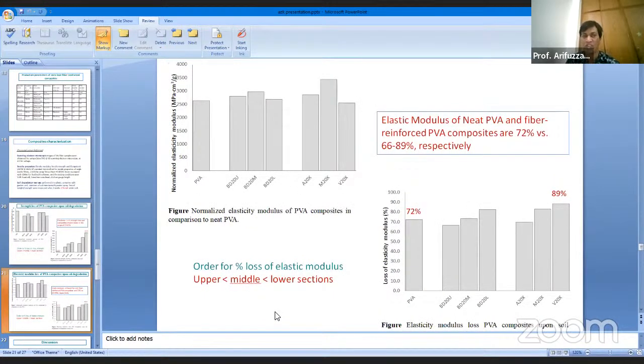In case of modulus, we get similar results. The upper figure shows the elastic modulus of the composite material before degradation, and the lower figure shows the loss of elastic modulus after degradation. We saw similar loss of elastic modulus for different types of fiber. The upper part shows less loss of tensile modulus, and the lower part shows the maximum loss of tensile modulus. And for chemically treated fiber, alkali treated fiber shows lower loss of tensile modulus, and the vinyl acetate treated fiber shows the highest loss of tensile modulus.